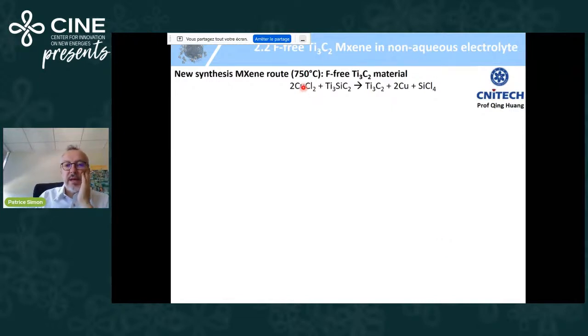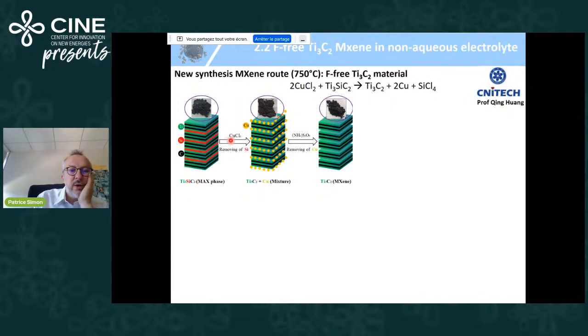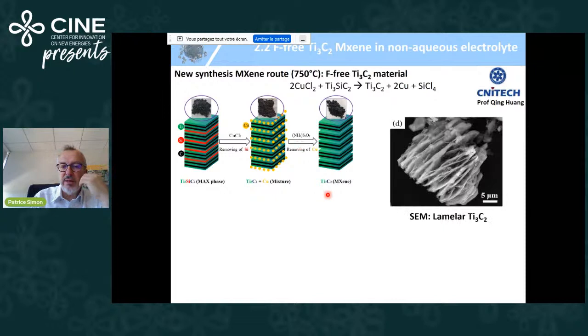You take a copper chloride and you heat this copper chloride at 750 degrees C. It's liquid. Then you put your MAX phase, Ti3SiC2. And silicon is going to be removed by oxidation into SiCl4 gas. And this silicon oxidation is induced by the copper 2+ reduction into copper. So during this process, copper 2+ is reduced, and you have a concomitant oxidation of silicon into silicon 4+. And then normally you have your MXene prepared, but with copper. So the second step is needed to oxidize this copper with APS, ammonium persulfate, to finally obtain the MXene.